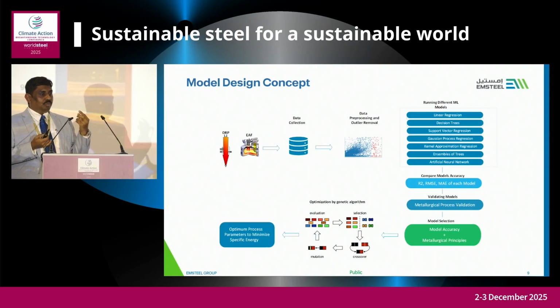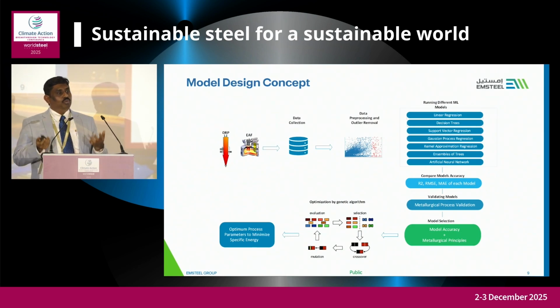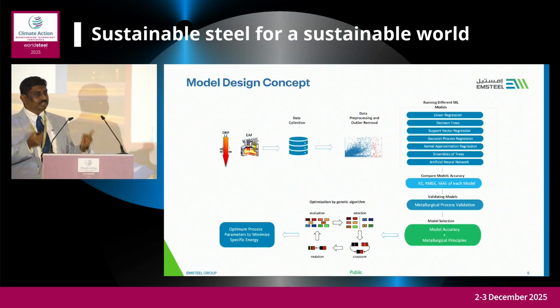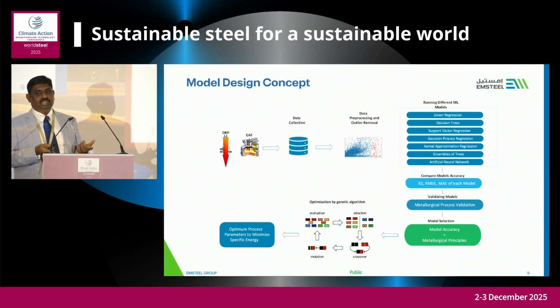We take parameters like, suppose in the electric furnace, we have 4 controllable parameters: oxygen injection, carbon injection, lime and dolo lime. Whereas the DRI that is coming in is not in our control. So we are maintaining the slag quality. What are the best parameters to optimize, to minimize the energy?